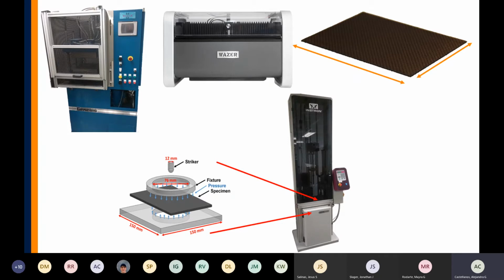In the case of the ships, this high temperature could be between 60 to 80 Celsius. So obviously we need to know not only what is going on at room temperature, but also what is happening at these different temperatures. So for this reason, we have this environmental chamber.